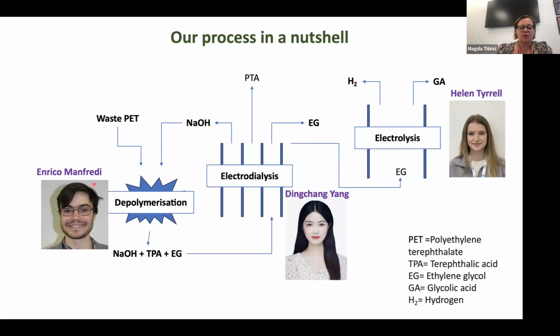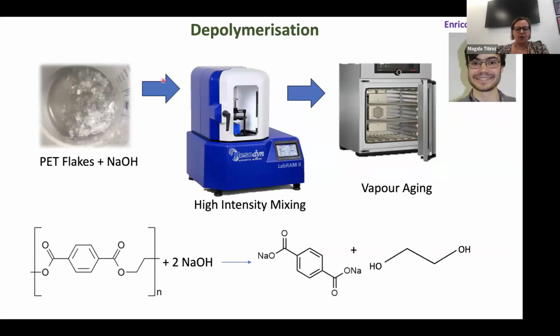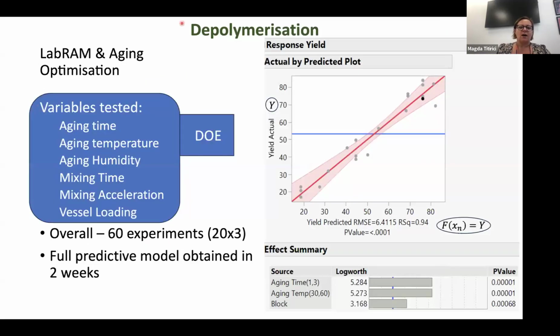And so we have 3 people: Enrico, who's doing the depolymerization, Ding Chang, who works on the electrodialysis, and Helen, who's doing the electrolysis. As I said, our process for depolymerization is relatively cheap. We are using these PET flakes with sodium hydroxide. We have a Resodyn acoustic mixer, and then we're aging the system for some time. We are trying to improve the kinetics here, and we're getting sodium terephthalate and ethylene glycol. We are also doing a design of experiments optimization to really improve the parameters for depolymerization, such as aging time, temperature, humidity, mixing time, and so on.